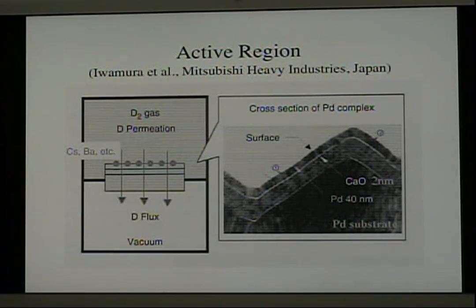First of all, they take a piece of palladium and pass deuterium through it. Deuterium is on one side and the vacuum on the other, so that deuterium is caused to diffuse through the palladium. Now, the palladium contains a number of layers on the front surface that consist of alternating layers of palladium and calcium oxide. These layers alternate in this region, and then finally there's a calcium oxide and a thicker layer of palladium. On this surface is deposited the target element. It can be cesium, it can be strontium, or it can be barium. And then it's simply exposed to the diffusion of gas.